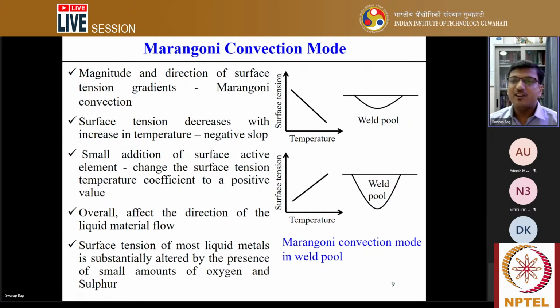So the material can be the same, and all welding process parameters can be the same, but the only difference is the application of a small amount of surface active elements in this particular material, and you can expect the shape of the weld pool to be different. The second case we can utilize in a beneficial way, because in that case it is possible to reach a high depth of penetration even for an arc welding process, and very low width, which is practically most useful as compared to the flat pattern of the weld pool. That's why there is the use of the surface active element.